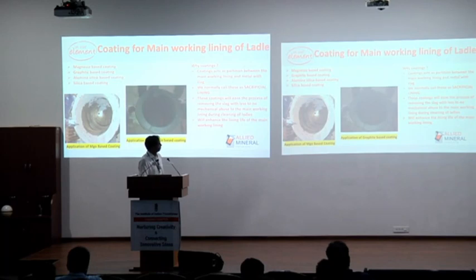So these are some coating materials we normally recommend along with the castable. We have magnesia based coating material, graphite based, alumina silica based and silica based. Why coatings? Normally coatings act as a partition between the main working lining and the parent working lining. And whenever you have metal and slag on the lining, the slag attacks only the coating product and not the parent lining.